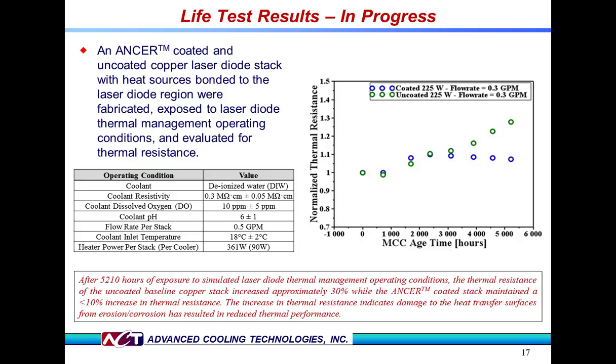Industry standard for meaningful life test results is 10,000 hours. Unfortunately, there is only one reliable way to do that, and it does take time. But here we show results for testing the stack configuration detailed in the previous slide after 5,000 hours. Operating conditions are the same as the previous slide. On the graph, on the y-axis, we plot the normalized thermal resistance against time. ANCER-coated samples are the blue circles, baseline copper are the green ones.